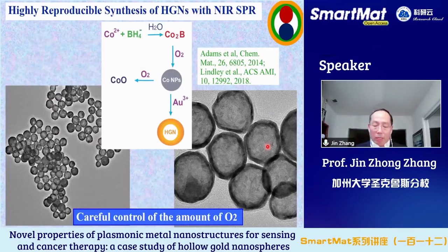At the end, here's the mechanism. It turns out oxygen plays a role in two critical steps, and actually there's a cobalt boride, tentatively assigned, that is produced first if you don't have oxygen. And with oxygen, we can produce a cobalt nanoparticle, which we use as a template to make the HGN. However, if you have too much oxygen, cobalt nanoparticles oxidize into cobalt oxide, which is not what we want. So that's a very tricky balance in the amount of oxygen. But in Sarah's paper, we talk about how we can control that very, very carefully. So we can make highly reproducible, highly uniform HGN today.